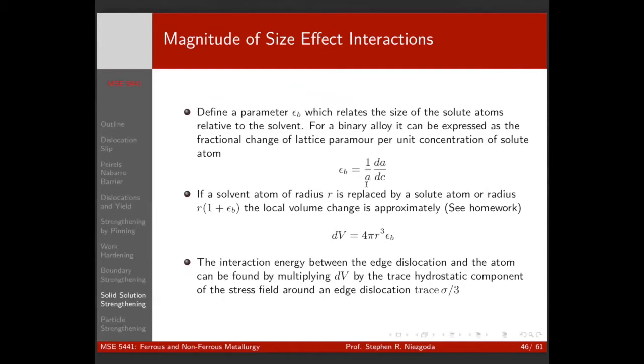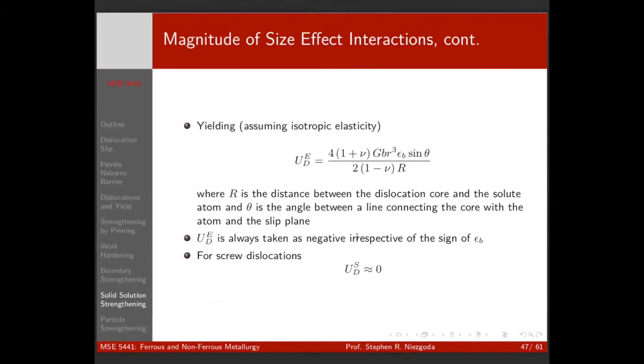So how big of an effect is it? Well, we can define a strain-like parameter that gives you the difference in lattice parameter per unit concentration of having the substitute in. And you can see that it goes as the radius of the matrix cubed, and then times the strain parameter, right? So that just sort of gives you a magnitude for it, right? And so if we substitute all this in, we get something.